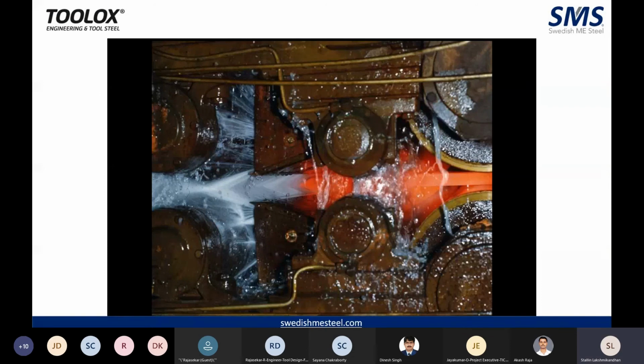So this gives the rough entire R&D of what is happening in the manufacturing of the plate. As you can see, the red hot plate has been water quenched and it turns to room temperature within a matter of seconds. This is where the entire R&D of the metal happens. Depending upon the different thicknesses of the plate, at which angle, and how much quantity of water is being quenched, that all decides the properties of Toolox.